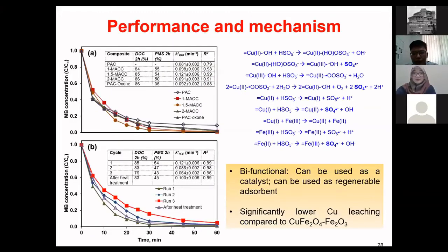What is interesting is that we found that if we make this kind of composite structure, we can have two different functions. You can use the activated carbon as an adsorbent itself. That means you can carry out a normal adsorption process. And then after that, you take the spent activated carbon and regenerate it. You can use this redox catalytic reaction to regenerate that catalyst. Another way to use this composite is as a catalyst. So one is as a regenerable adsorbent, the other one is as a catalyst. And in terms of the leaching, we found that it's significantly lower. It's less than 0.1 milligram per liter of copper leaching out from the composite.